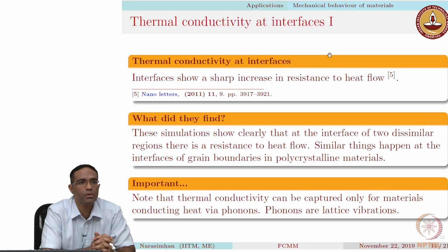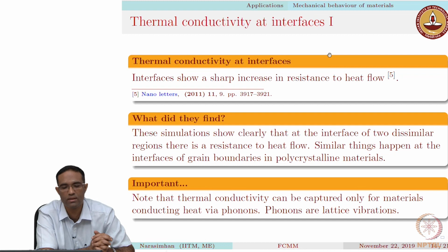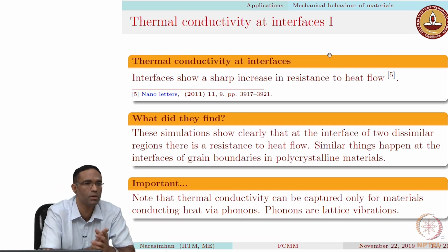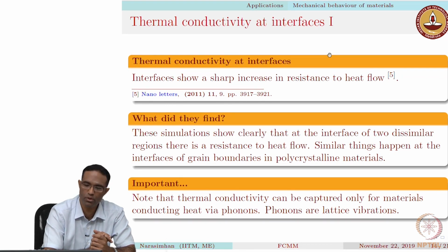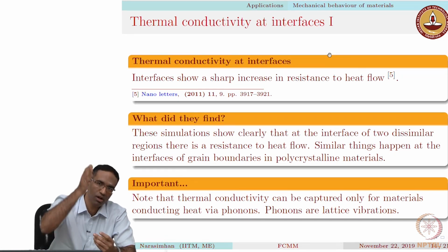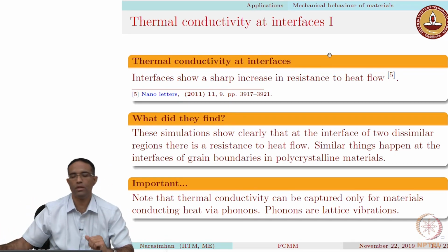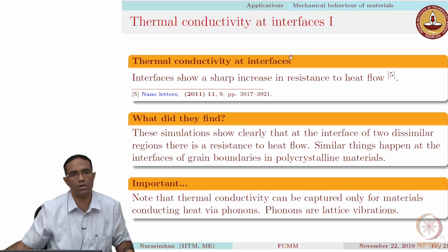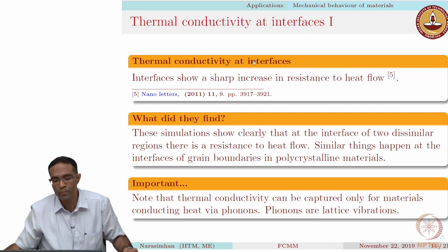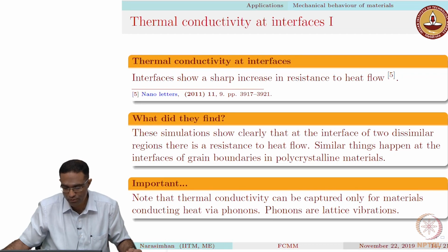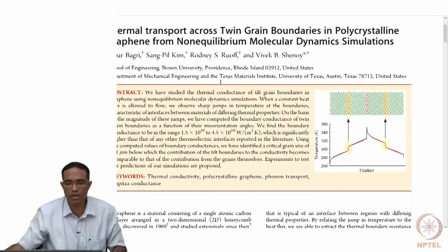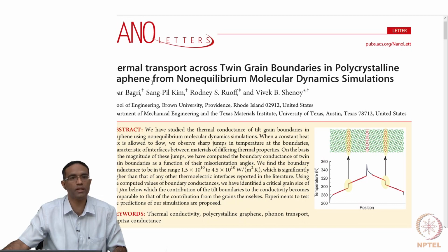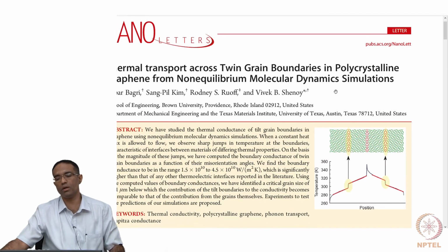Another example where it can be used in the thermal area is to determine thermal conductivity at certain interfaces. You can determine the thermal conductivity of some materials even in their bulk phase. But what is interesting in this particular article that I'm about to show is a manner in which the presence of certain interfaces causes a sharp increase in the resistance to heat flow. This is from a paper in Nano Letters: thermal transport across twin grain boundaries in polycrystalline graphene from non-equilibrium molecular dynamic simulations.